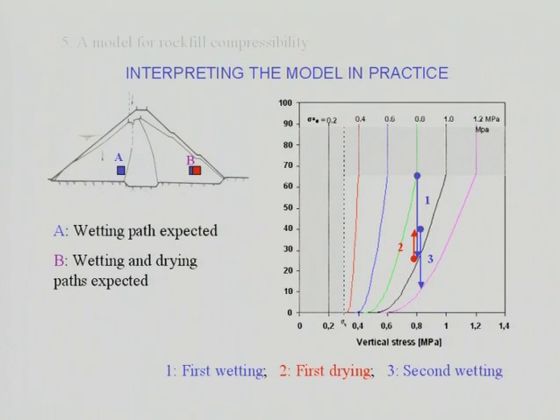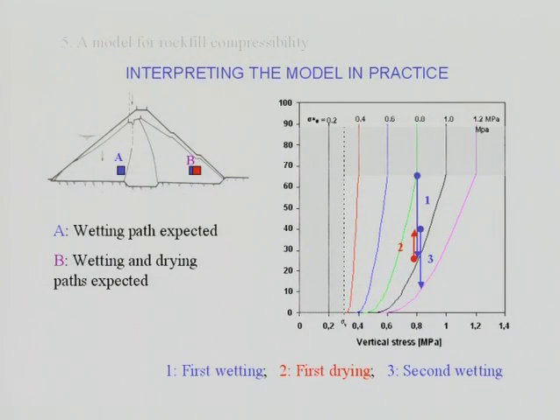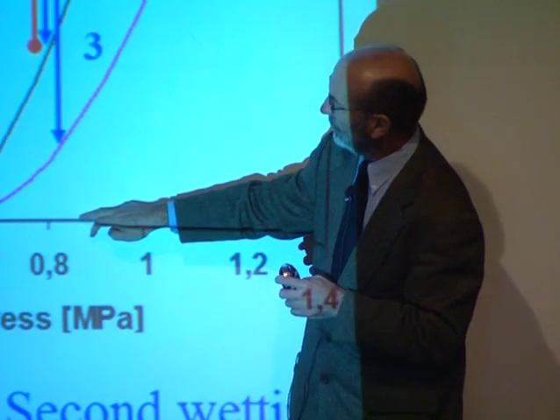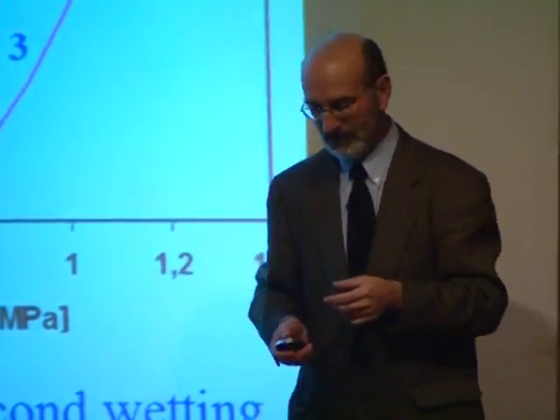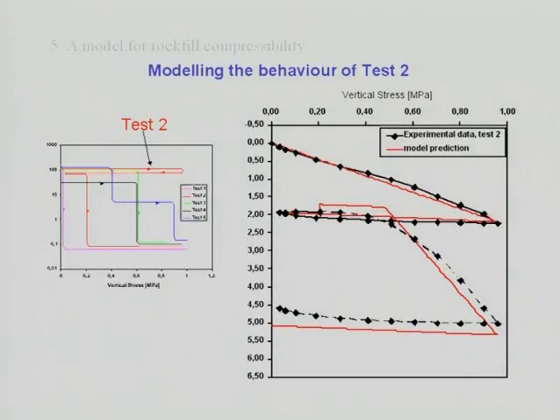And then you may dry it because there is some evaporation here, and then you will follow this path number 2. And here, nothing will happen essentially. Maybe some shrinkage, but in a rock fill, you won't notice almost anything. But then you wet it again, this is a second rain, and it will take you irreversibly to a third point here. Eventually, if you apply strong cycles of wetting, you may get to this saturated situation here. Your yield locus will move towards the right, and from that point on, nothing will happen essentially. And this is what actually has been measured in many rock fills, and I mentioned that to you before. Now, this is how the model fits one of the tests, test number 2.